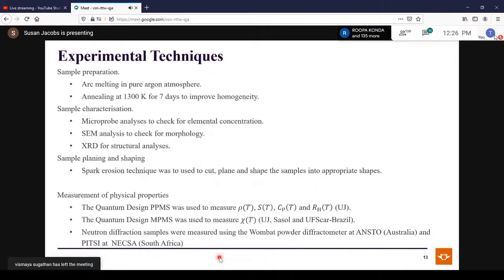For Hall effect measurements, by trial and error, we found that the best Hall effect measurement was for a sample with thickness 1 millimeter, and the length to breadth ratio is 3:1. So you would have a typical Hall sample of 18 by 6 by 1 cubic millimeter. So those are the different shapes we use for the measurements.